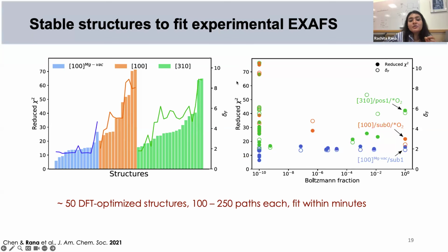What you see on the right is another powerful way of combining experiments and theory, where you have the goodness of fit parameters for EXAFS on the Y1 and Y2 axis, but you have the Boltzmann fraction, which suggests how well a material can be present in a specific energy state, on the x-axis. And so for each of these facets that we had in the database, I've pointed out the three most stable structures. Now, if we just look at these two plots, what we can see is that we know that the 100 Mg vacancy should be the best EXAFS fit.